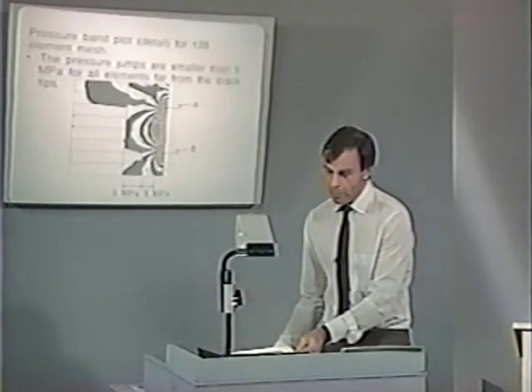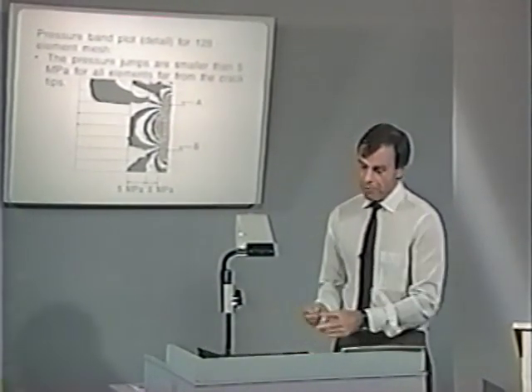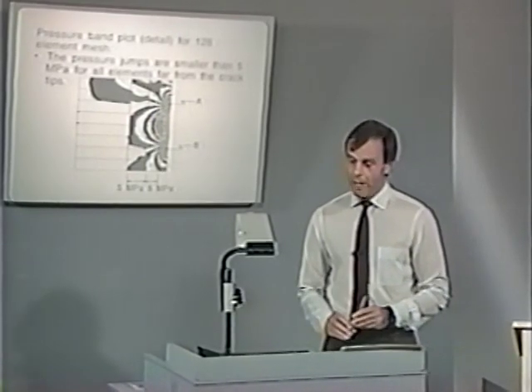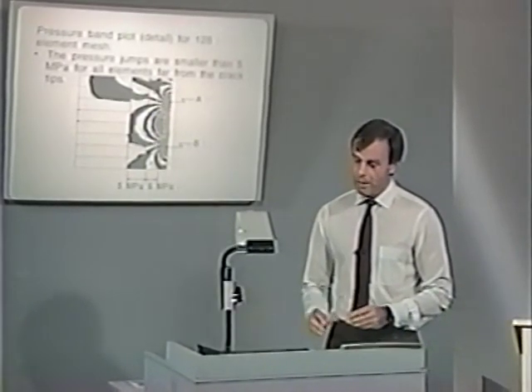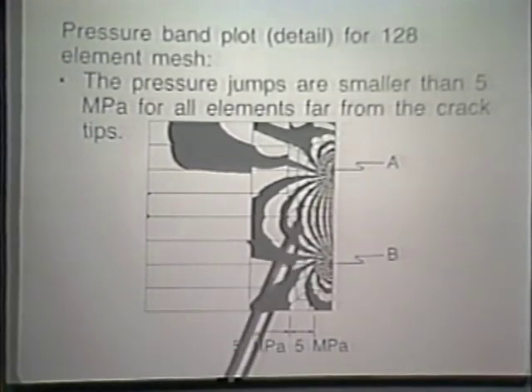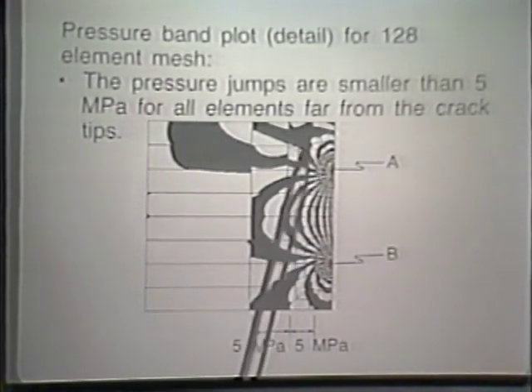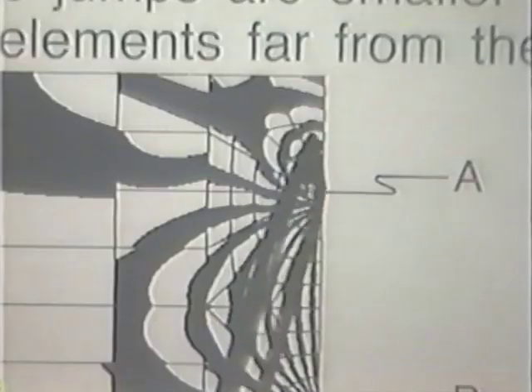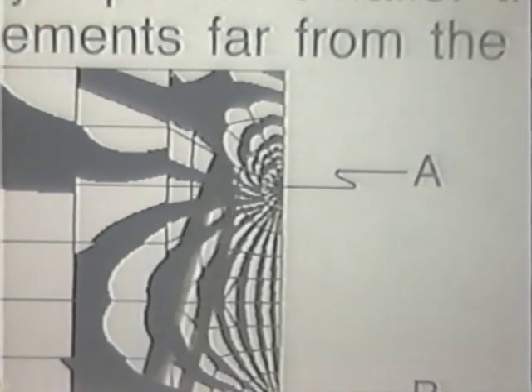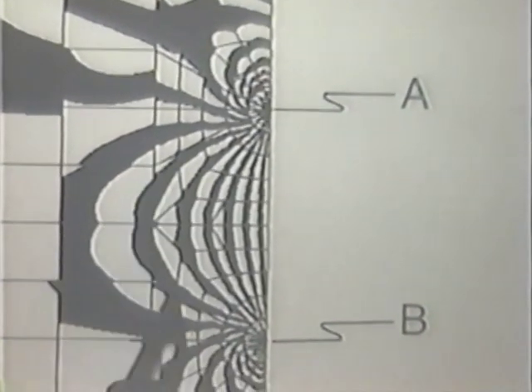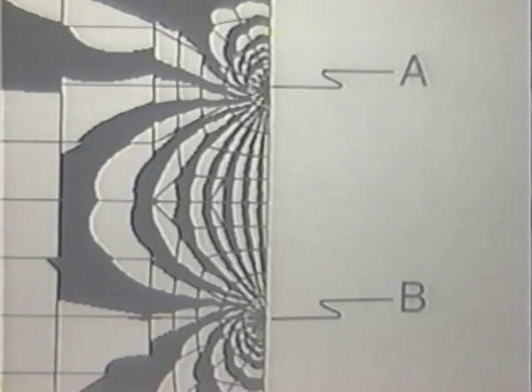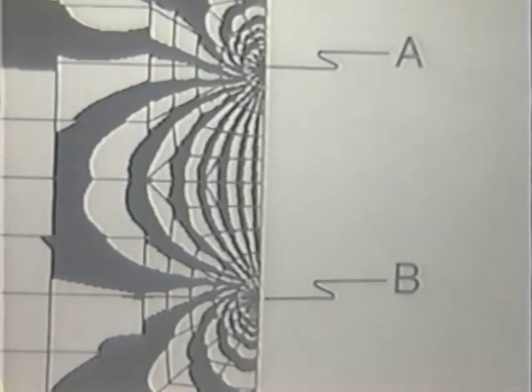But we can also look at our pressure bands again. We find that the pressure jumps are quite small if we go not too close to the crack tip. In other words, here we have some pressure band variation, some pressure band breaks, I should say. But we have two quite smooth bands that tell us that the mesh is quite fine.